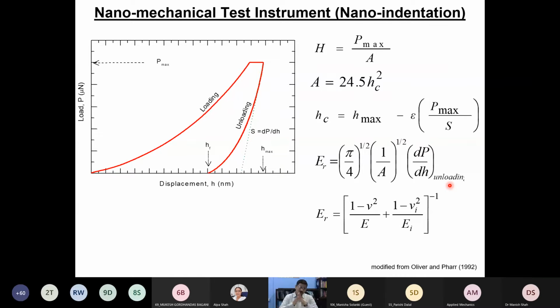By doing nano indentation, you are monitoring how the hardness and modulus of a polymer change at the surface level, a few micrometers deep, because this is where the polymer is aging. The bottom layers may not be subjected to any kind of photodegradation during the initial period.